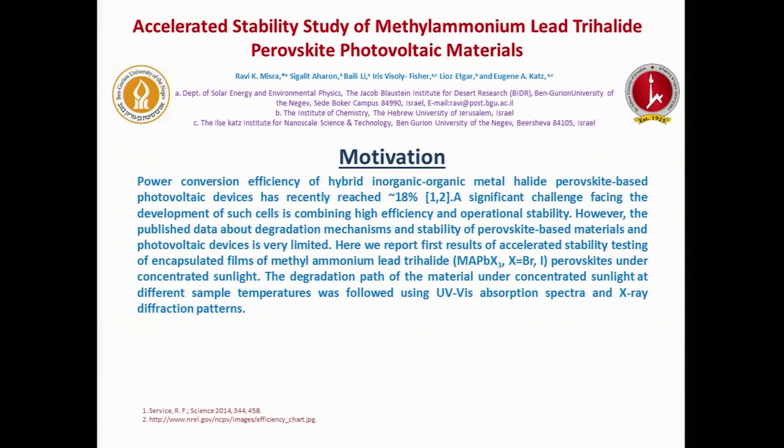Actually, Thomas and Professor Hahn and now the speaker told all about the cells. Now we are giving attention towards the stability of the material itself. For this, we did an accelerated light stability test, in which we tested encapsulated films of the material under concentrated sunlight conditions of 100 suns. In this, we used the material methylammonium lead iodide and bromide.